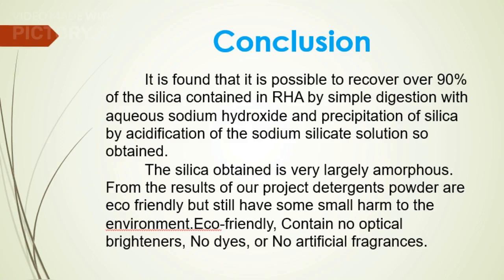In conclusion, it is found that it is possible to recover over 90% of the silica contained in raw rice husk ash by simple digestion with aqueous sodium hydroxide and precipitation of silica by acidification of the sodium silicate solution so obtained. The silica obtained is very largely amorphous. From the results of our project, the detergent powder produced is eco-friendly, containing no optical brighteners, no dyes, and no artificial fragrances, though it may still have some small environmental impact.